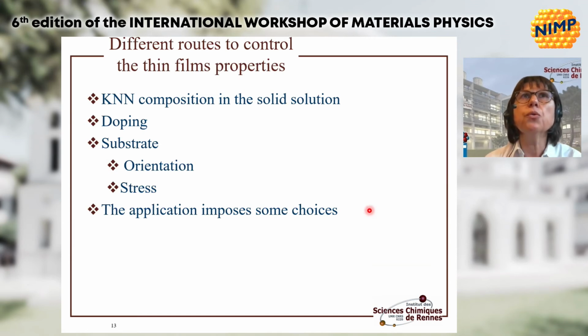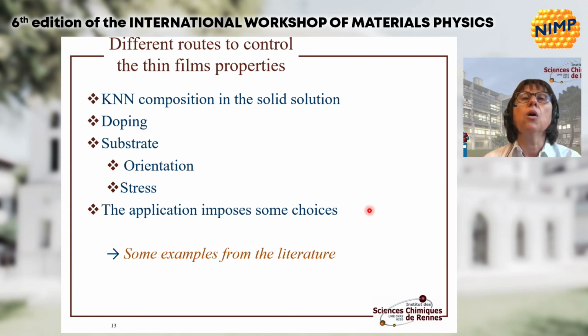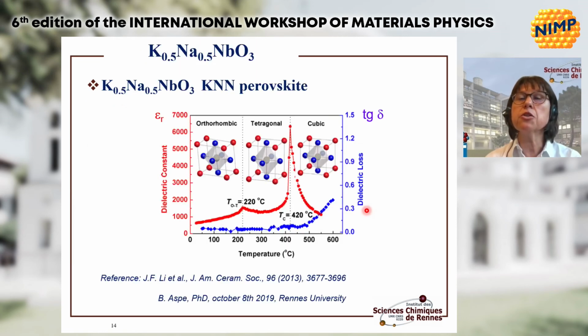So, how to control the thin film's properties and the KNN properties? The composition is the first solution. I will show you some examples from the literature. With the composition, we will change the structural features concerning the transitions, especially the morphotropic one. For instance, for the 50-50 composition, 50-50 ratio between potassium and sodium, we can see that this morphotropic transition will be from tetragonal to orthorhombic by cooling the temperature. Changing the composition in the solid solution will tune and change these phases.